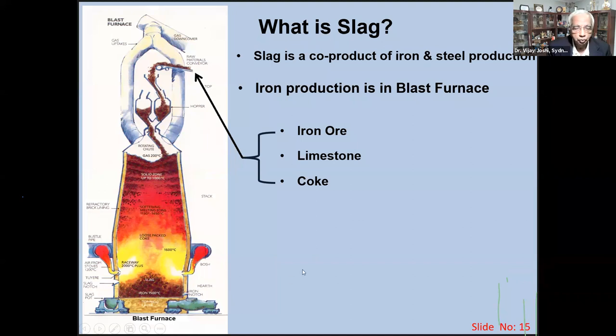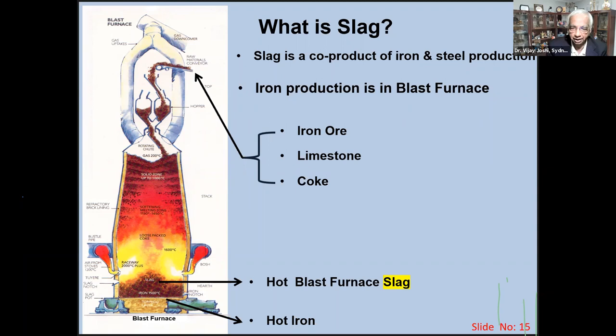Once the iron ore melts down, obviously you get the hot iron. But hot iron, because it is a liquid metal, will remain at the bottom of the flow because it contains the heavy metal. While slag is also part of that flow, slag means all the oxides, so the specific gravity of the slag is low compared to hot iron, and it floats in the channel. Then you separate the channel, so blast furnace slag is separated and the hot iron is separated.